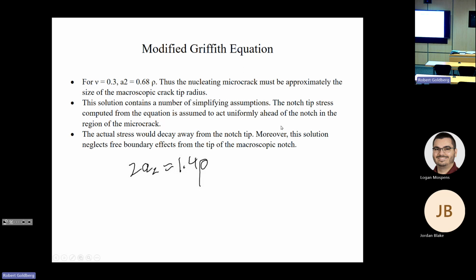So 1.4 is a little different, but it's not like it's 10, 100, 1,000. So for this little micro crack to affect the big crack, it has to be at least as large as the crack tip radius. Now, this solution contains several simplifying assumptions, as most simple problems do.